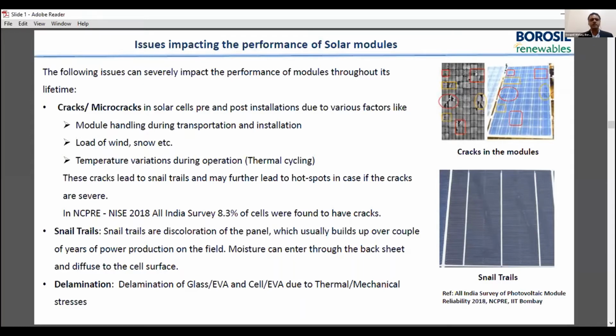These cracks actually lead to snail trails, which are apparent in the picture down below. This may further lead to hotspots in case these cracks are pretty severe. There is a study done by NCPRE, which is a part of IIT Bombay, in 2018. They found that around 8.3% of the cells had some crack, micro crack or major cracks. That's why we need to be very careful. Since the module design is also driven by glass, if the design is not done properly, there is a risk of cracks or micro cracks, which will ultimately spoil the